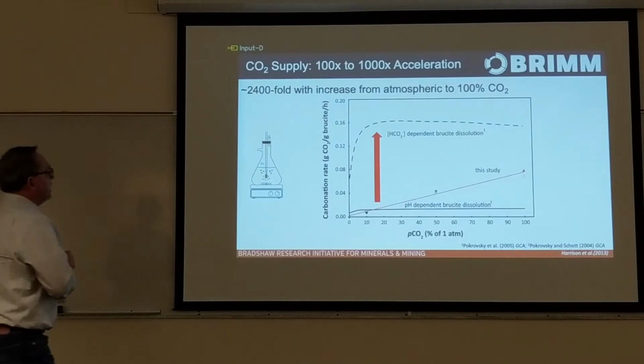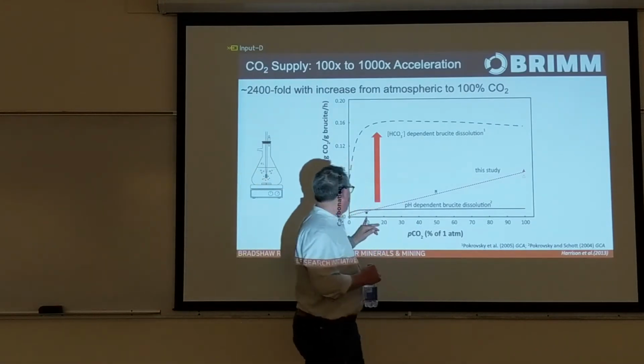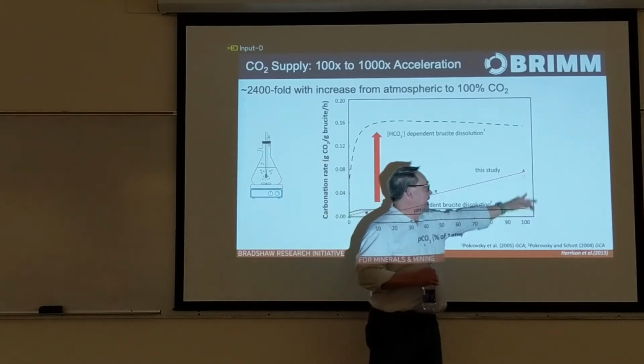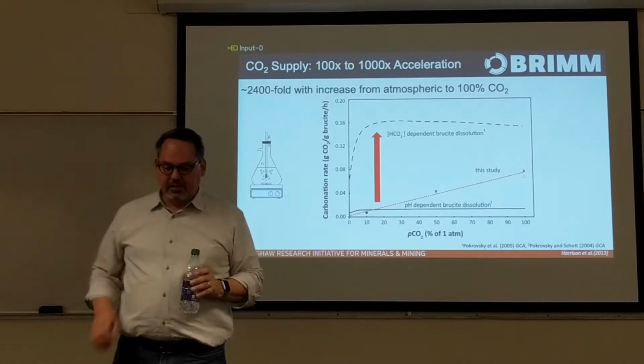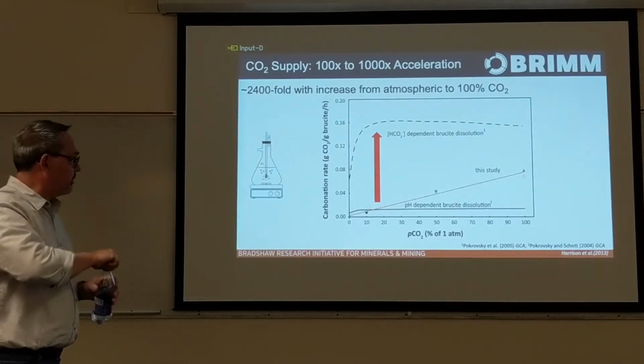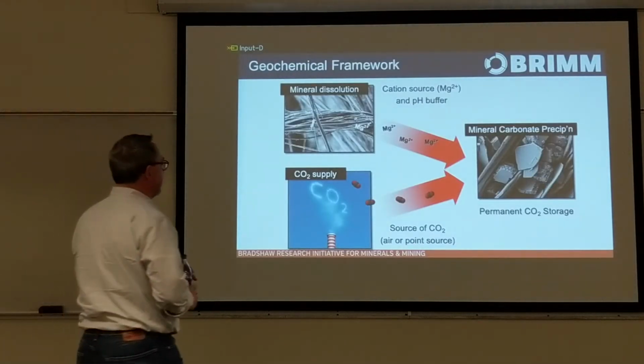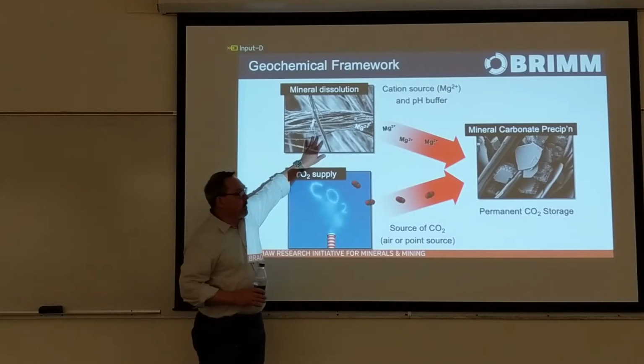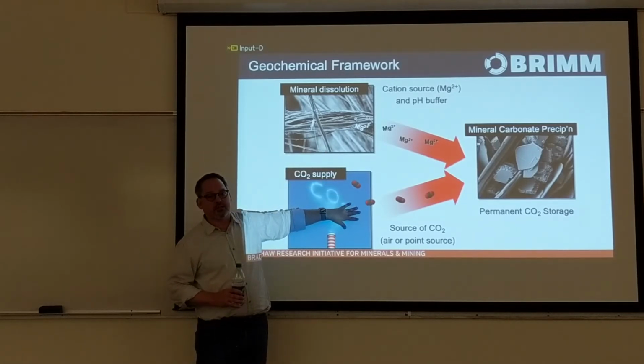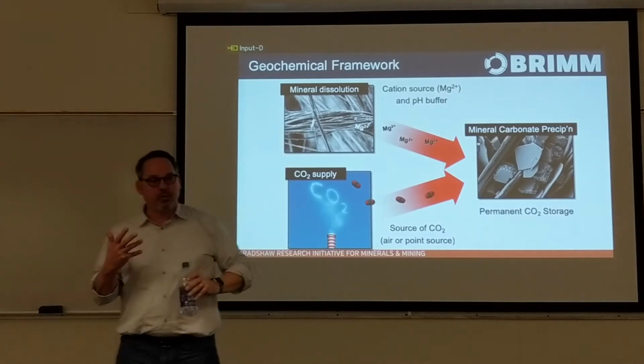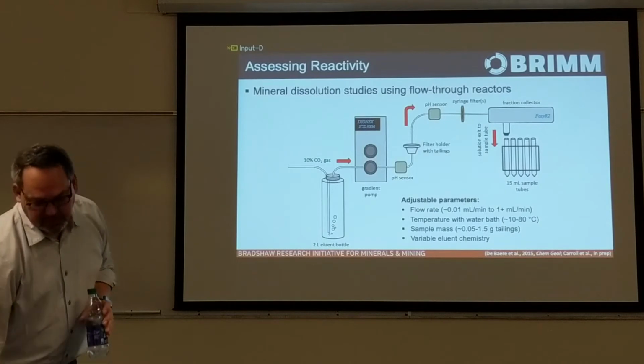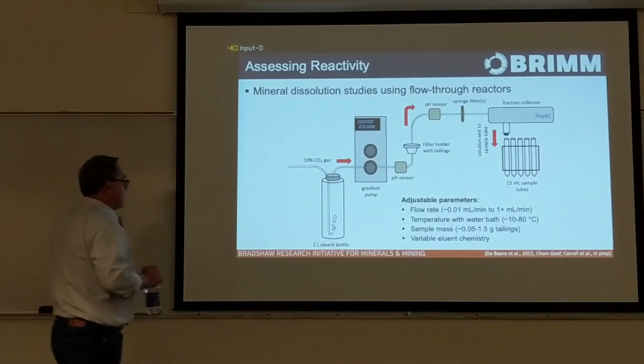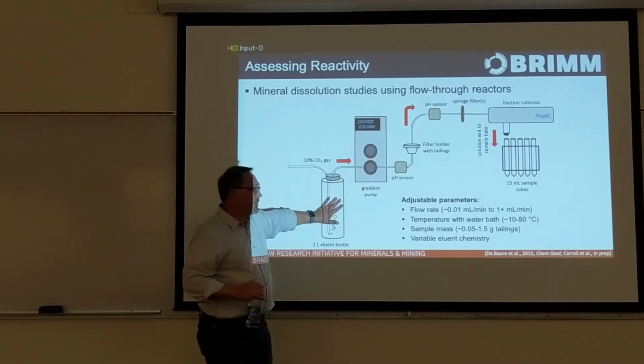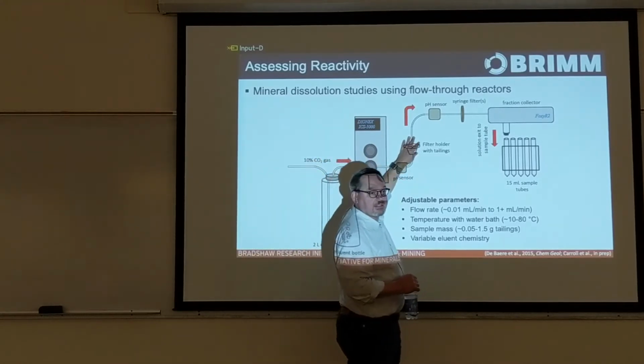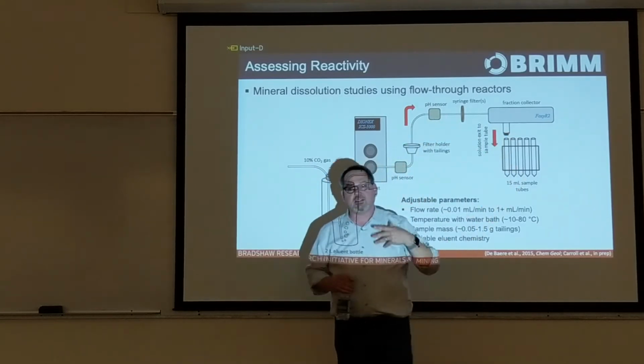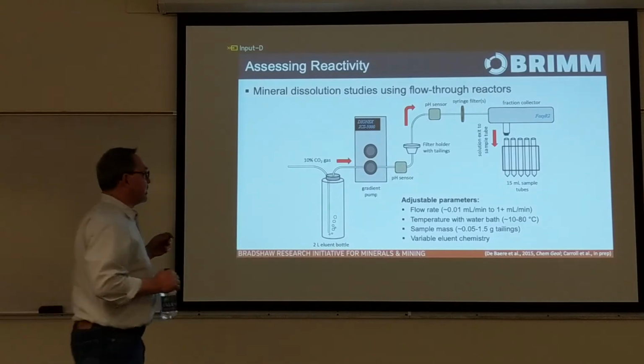And Anna Harrison, in her PhD, showed how we can get about a 200-fold acceleration using flue gas over air, and if we have pure CO2, we get about 2,000-fold acceleration of CO2 reaction rates by using concentrated sources of CO2. So there's a whole bunch of ways that we can get past this obstacle. What our work is now really focused on is, if we're going to take one of these scenarios and deploy it, we want to deploy it to the most reactive materials. And how do we understand what the most reactive materials are? To do that, we use a custom-built mineral reactor. Essentially we have an eluent that is pumped through a sample of tailings. We measure the pH before and after, and then we auto-collect that solution at the tail end and measure the cation abundance, so we can get mineral dissolution rates.